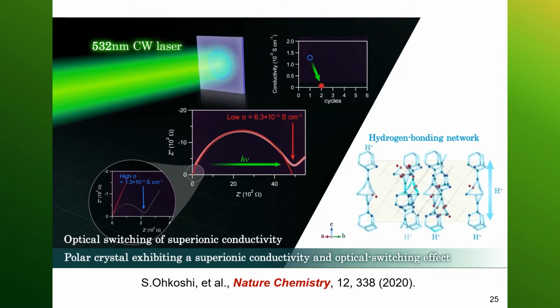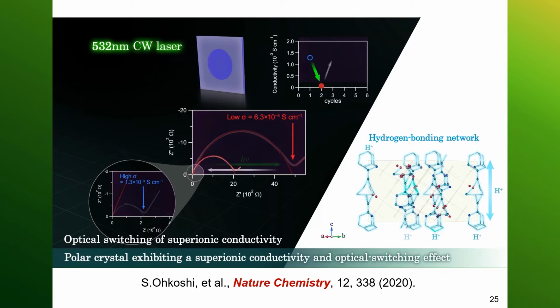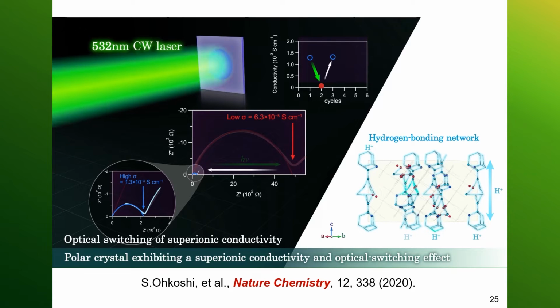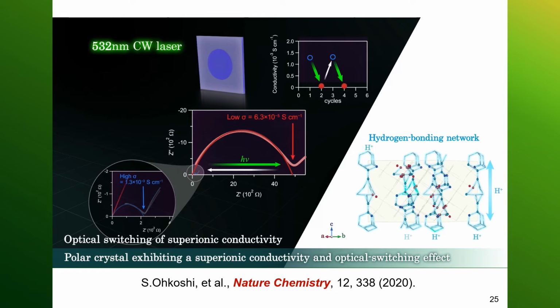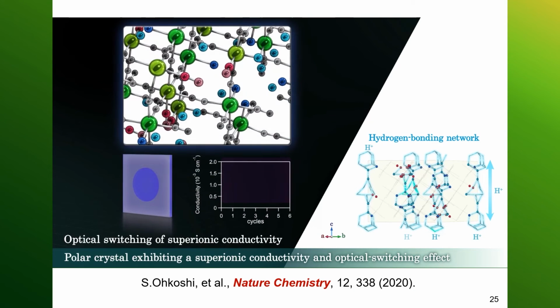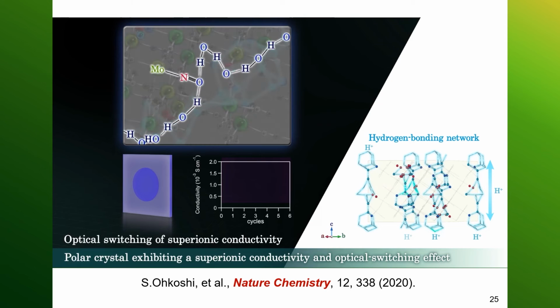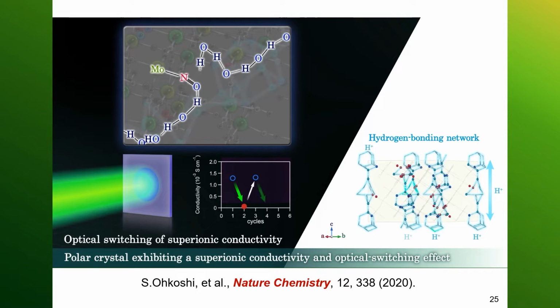Irradiation of light results in changes in proton conductivity. The level of conductivity of this material is very high, falling slightly below the proton conductivity of Nafion. Irradiation of light changed the internal structure. Molybdenum NO inside results in switching on and off of hydrogen bonding network with changing angles which change proton conductivity.